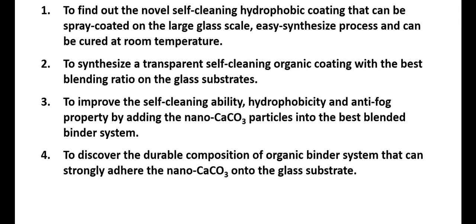Photovoltaic panels have a glass substrate on top, or building glass, so we have only glass materials. Another thing is to discover the durable composition of an organic binder system that can strongly adhere the nano calcium carbonate onto the glass substrate, because we need a proper binder system that can hold the nano calcium carbonate onto the glass substrate and within the coating system. So that is the reason.